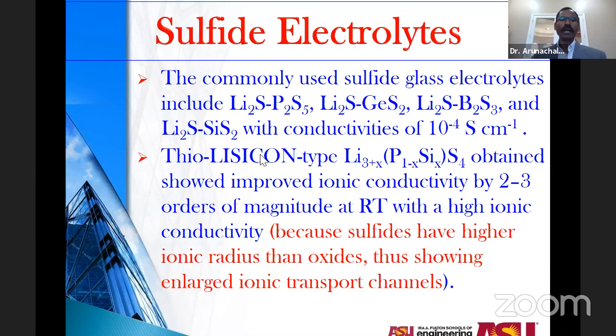And you can also have a combination of modified silicon with a sulfide, because these are the sulfide materials, and that could actually show higher conductivity, probably 2 to 3 orders of magnitude compared to other materials. That is mainly because of the relatively larger ionic size, or higher ionic radius, of the sulfides compared to oxides. That would actually open up larger transport channels, so lithium ions can easily go through the structure to have higher conductivity.